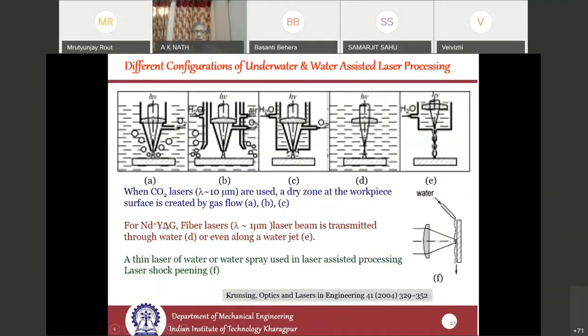There are different ways in which underwater processing has been done. Here, the laser beam has been put along with a high pressure oxygen or air pressure, so that where the laser beam is falling, a dry condition is created. Here, by putting a very high pressure gas jet, you have made apparently dry atmospheric conditions. So in these two cases, you have got the dry conditions created by the high pressure gas. And here, along with the laser beam, you are getting the water also, and creating the dry conditions and doing the weld processing.